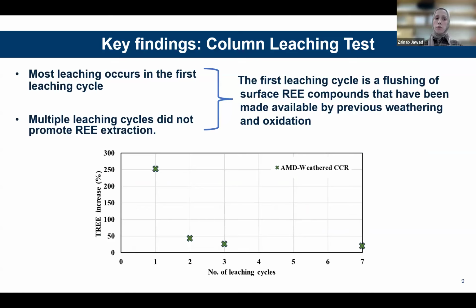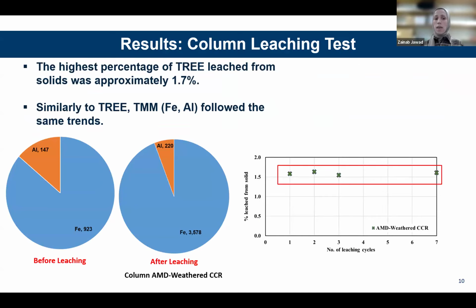Also, another very important key finding is that most of the leaching occurred within the first leaching cycle. The multiple leaching cycles that we did during weeks 5 and 6 did not promote RE extraction. And that, again, as I said before, is because prior weathering and oxidation had made the RE compounds available at the surface. So the first cycle was enough to flush most of the REs out, and we didn't see any significant increase after that. Another result is that the highest percentage of total RE leached from the solid was less than 2%. And total major metals, for example iron and aluminum, followed the same trends that we've seen with the total REs.